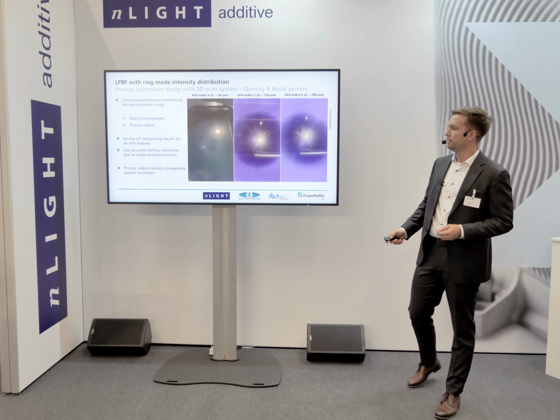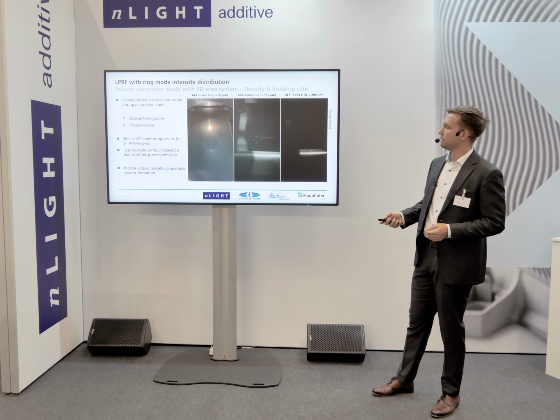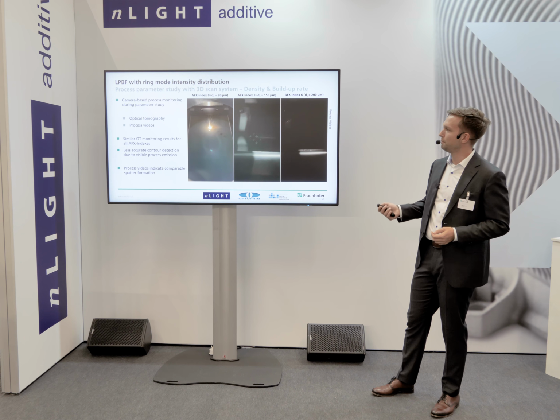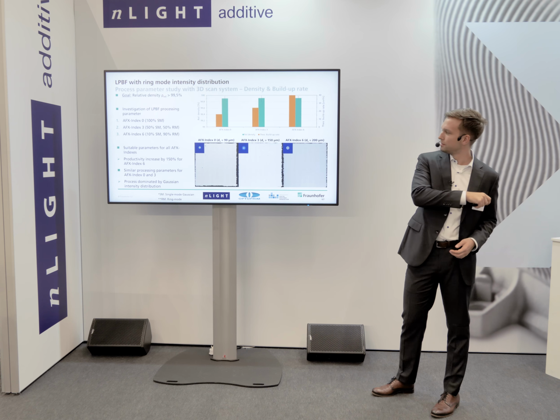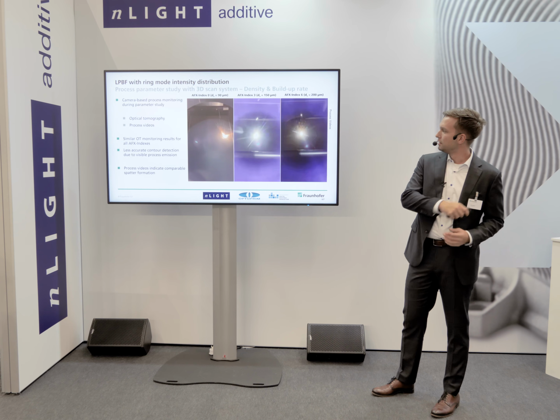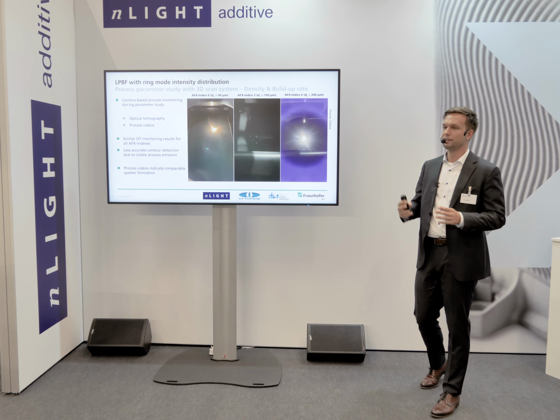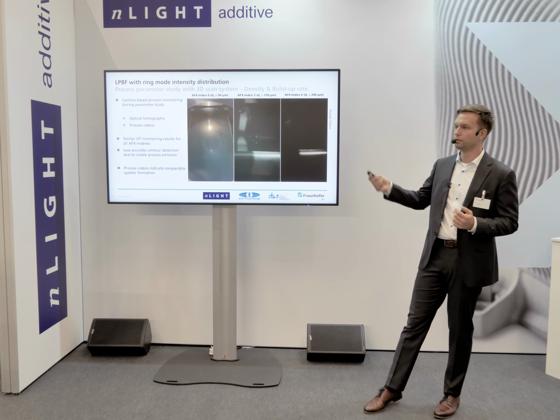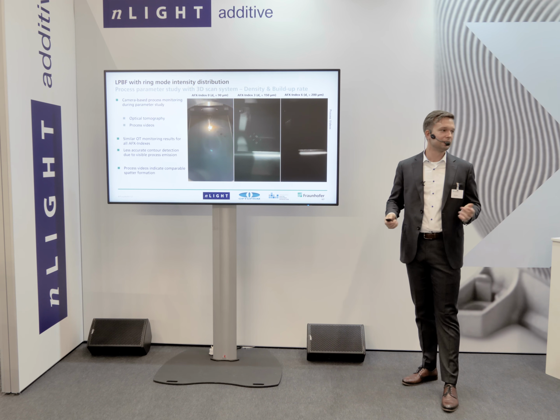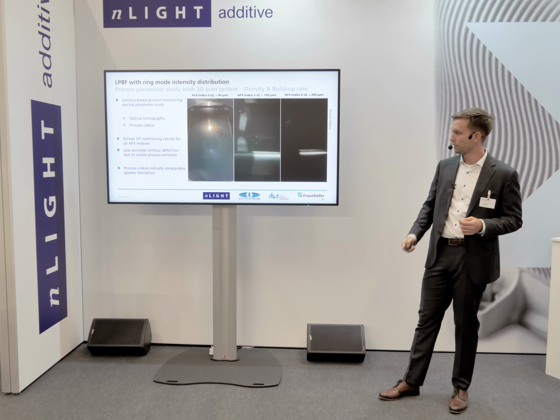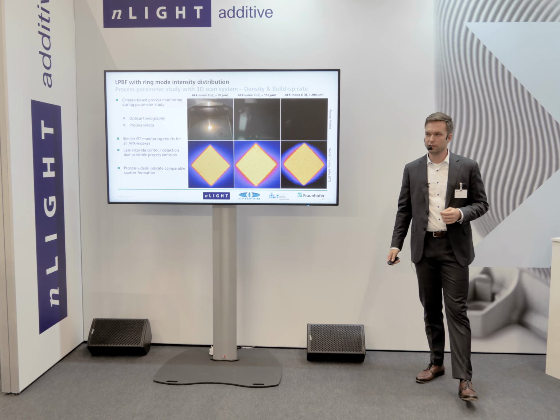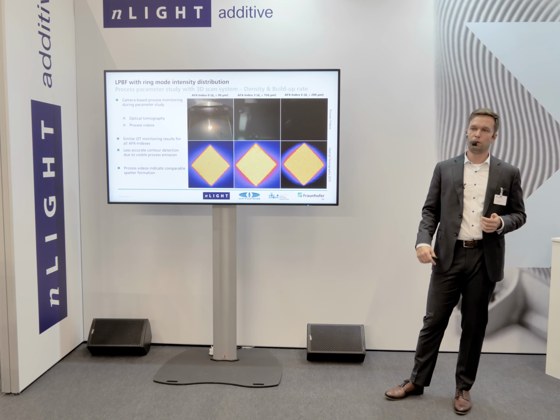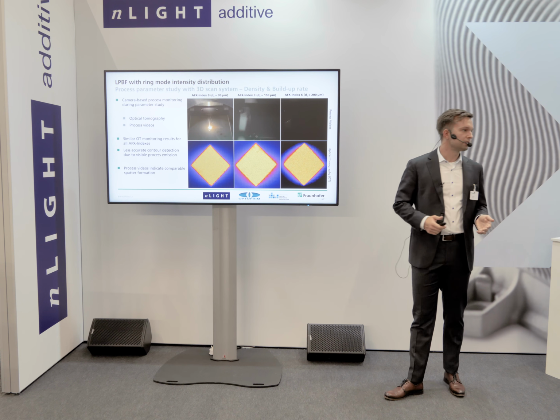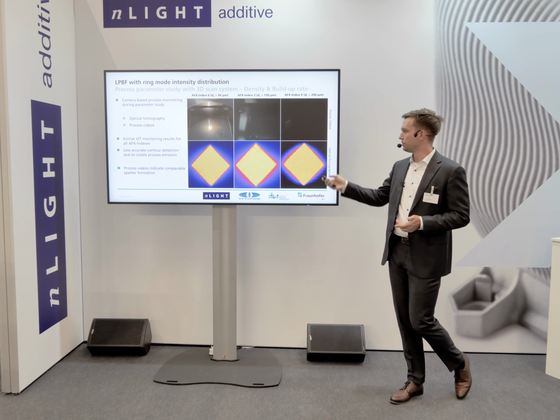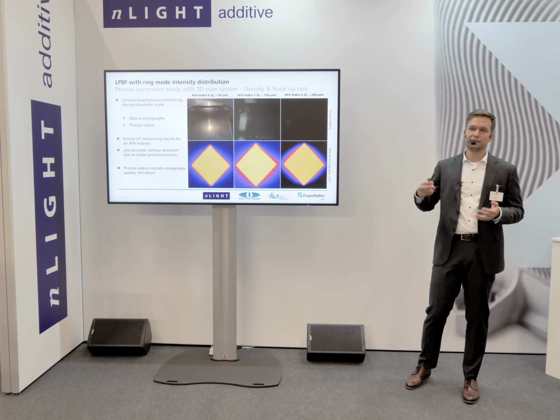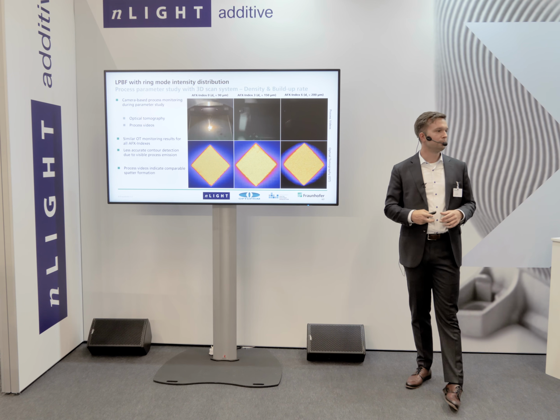I also included some videos, and also here you see the AFX index 6 process, and I will skip back and play it again if it works. It's just way faster. So in the time one of these test cubes is exposed in the left video, already 3 cubes are processed in the right-hand video. And we also did some OT process monitoring during the builds, and we found that there were no major deviations, so no cold or hot spots in the process. You see that the part contour is a bit overexposed in these images, but this is just due to the fact that the process emission at these higher laser powers is generally stronger.